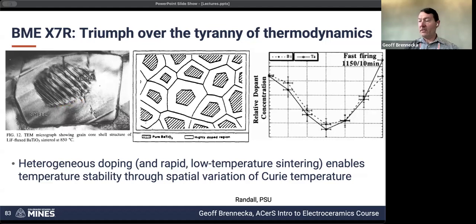So the sketched cartoon version of it is shown here, where they're claiming it's pure barium titanate surrounded by a highly doped region. The first version of this really was you start with pure barium titanate and then put in stuff at the grain boundaries that will diffuse in so that you get a gradient in doping concentration. And this is what's shown here, where they're using bismuth and tantalum as the dopants that would help form this core shell structure. That was just the first generation sort of proof of concept. People have moved well beyond that just simple doping at the grain boundaries perspective, but the concept sticks around.